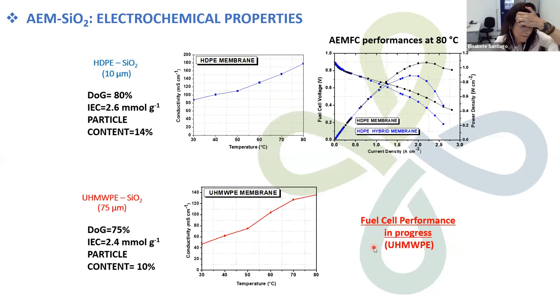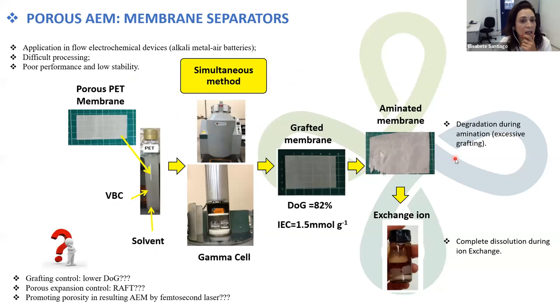You have obtained very, very good conductivities despite the silica being an insulating component. But you have obtained very nice conductivity, and the performance is expected to be lower than the unmodified membrane, but it's not too far. Right? The difference is not so big. Okay. We have worked with high density polyethylene and ultra high molecular weight polyethylene because the membranes are very susceptible to grafting, and you can obtain materials with very good content of silica.